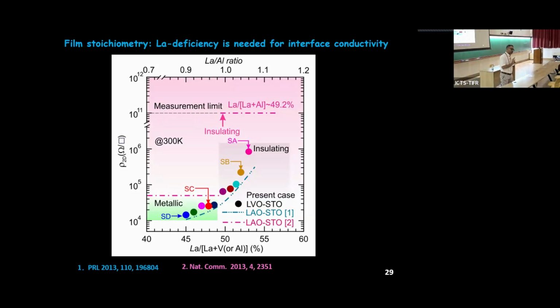Yes. So if you see, this has a remarkable correspondence with what people had seen for the LAOSTO system and our deposited LVOSTO system: if you have a strontium or lanthanum deficient material, it becomes conducting, but when it becomes lanthanum rich, it becomes insulating.